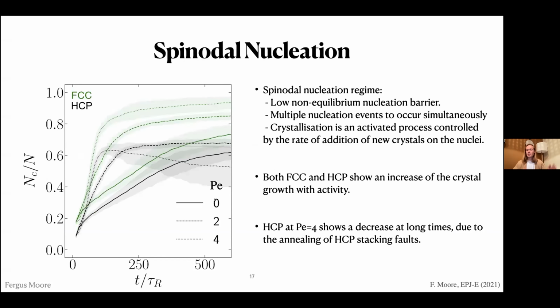And finally, we look at the spinodal nucleation regime. What I'm showing here is how these spinodal crystals grow very quickly for different Peclet numbers. We have the green and black lines for FCC and HCP as before, and we're looking at three Peclet numbers: 0, the passive case, and the dotted lines are Peclet 2, and the smaller dots are 4. You can see as you increase the Peclet number, the rate at which these crystals grow increases because of the accelerated dynamics. You also see, for example, in Peclet 4, the HCP will decrease over time as we have annealing of stacking faults.